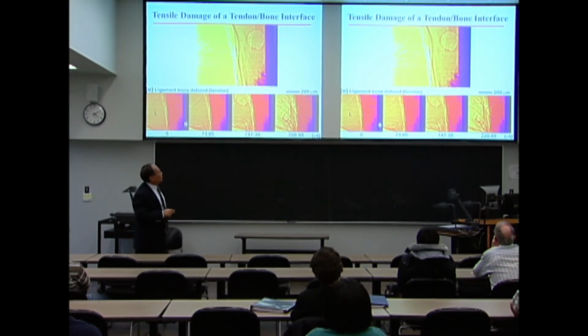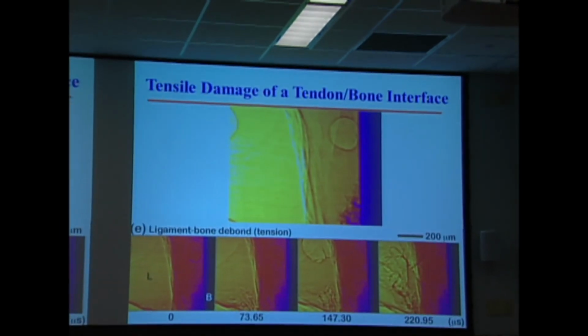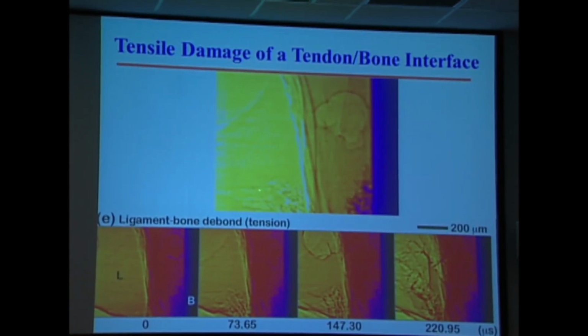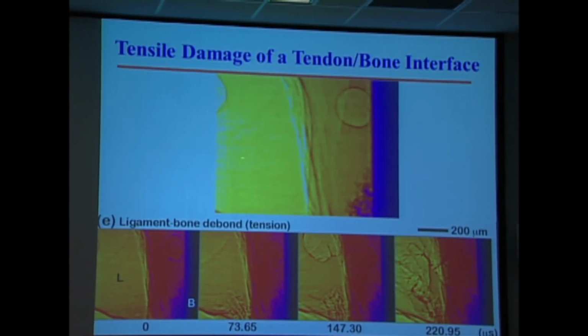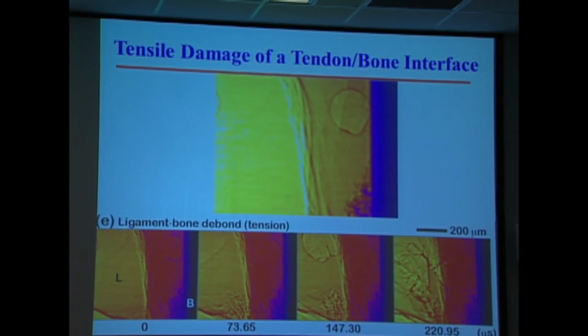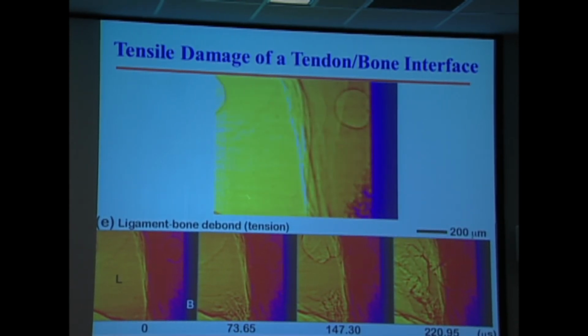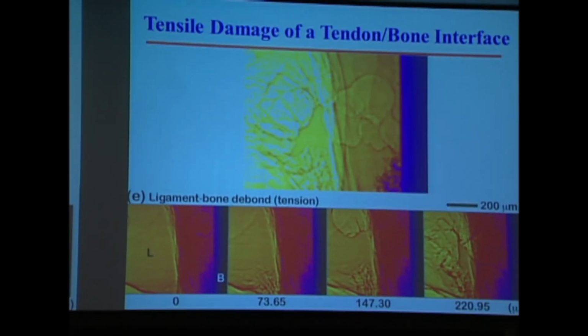This is the example I'm going to show you of the power of this phase contrast imaging X-ray technique. This is a joint between a bone and a tendon, and we're pulling apart the interface at a high rate. Then you see the detailed features show up in the tendon. In the regular X-ray radiogram, you're going to see the bone in dark, and the rest of it is a cloud. We see a lot of features inside the tendon, how they got pulled away from the interface. What's the procedure? Where does it break first? The only problem is that we don't know how to explain what we saw.